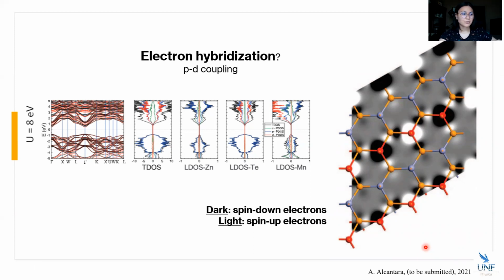This figure was made to show what all these lines mean exactly. So for comparison, I have here the 50% doped at U equals 8 to show what we have here. So electrons have a spin up or a spin down, and the spin downs are the darks and the lights are the spin ups. The red is the manganese, the orange is tellurium, and the purplish blue is the zinc. And as I had said, the zinc is essentially being ignored from the system. That's why it's surrounded by a mostly gray area.